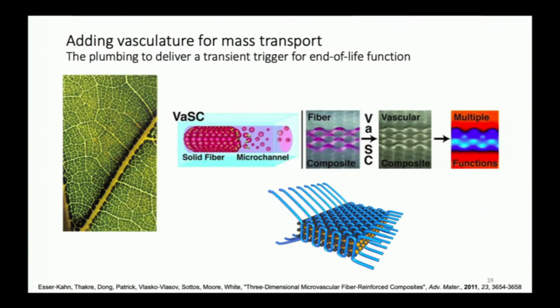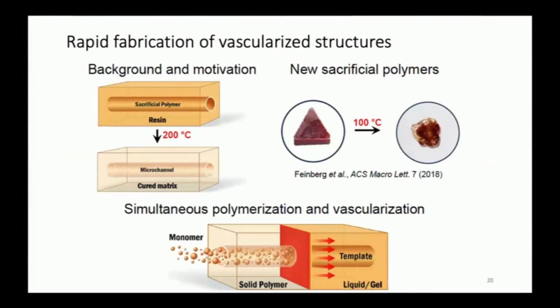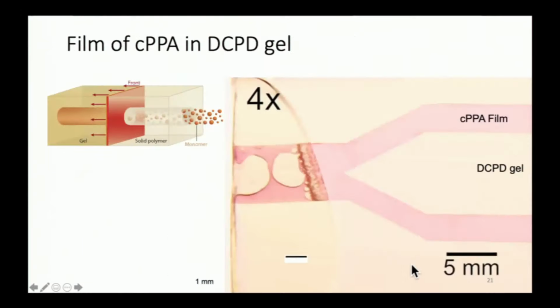And the real question then is, can you efficiently manufacture composites? Some recent work in the lab begins to look at some of these same materials I described earlier. Adam Feinberg's work with the cyclic phthalaldehyde that I showed earlier is a sacrificial material that is thermally degradable with the appropriate additives. And so you can imagine that this is a solid filament of sacrificial polymer made out of this material, heated at something near 200 degrees C, which, by the way, is the typical temperature at which frontal ring opening metathesis polymerization takes place, will cause the sacrificial material, as you can see in the schematic at the bottom, to be removed.